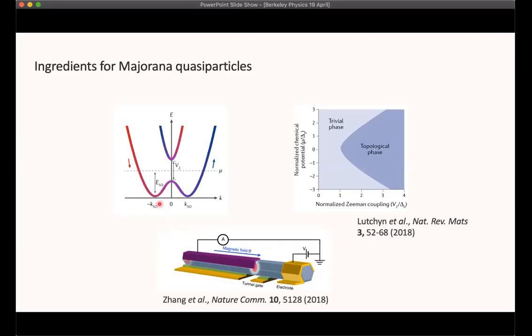Strong spin-orbit coupling will give a momentum-dependent shift to an energy spectrum. And now, if in addition to strong spin-orbit coupling, we apply an external magnetic field orthogonal to the spin-orbit coupling field, so here in blue is the orientation of the magnetic field in this problem, then we lift a gap at zero momentum in the energy spectrum. And so then if we tune the chemical potential of the system so that it lies inside this gap, which we can do by applying electric fields with, say, local gate electrodes, then we find that we have an effective single band model. And an effective single band model looks a little bit like a spinless model.